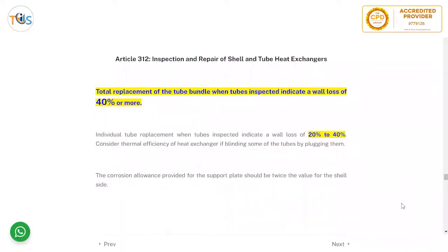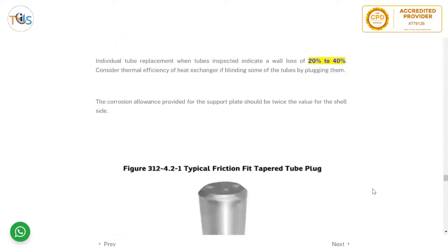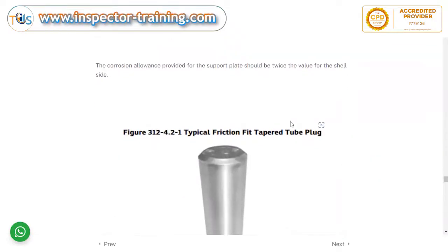Inspection and repair of shell and tube heat exchangers. Total replacement of tube bundle when tube is inspected indicate a wall loss of 40% or more. So if it is more than 40%, then do the total replacement. Individual tube replacement when the wall loss is 20 to 40%. Consider thermal efficiency of heat exchanger when blinding some of the tubes by plugging them, and the corrosion allowance provided for the support plate should be twice the value for the shell side. So remember that it's twice the value.